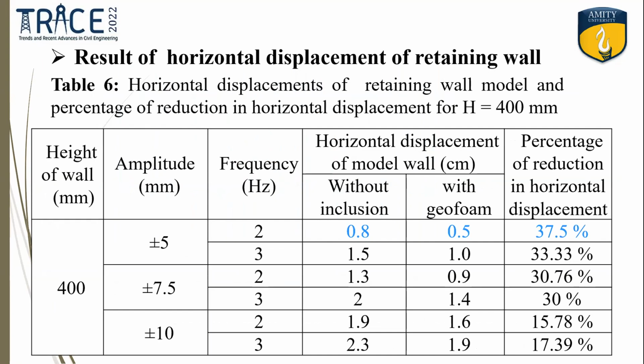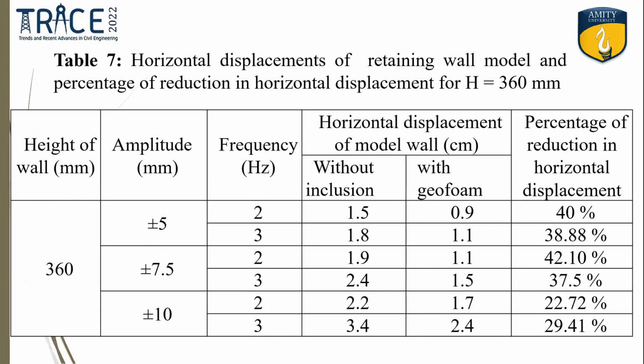model and the percentage reduction in horizontal displacement for model height h equal to 400 mm. For 5 mm amplitude and 2 Hz frequency, when geofoam is not provided, the horizontal displacement of the wall is 0.8 centimeter, and when we provide geofoam, it reduces to 0.5 centimeter, and the reduction in this case is 37.5. Horizontal displacement of the model and the percentage reduction in horizontal displacement for h equal to 360 mm model height are shown in table 7.